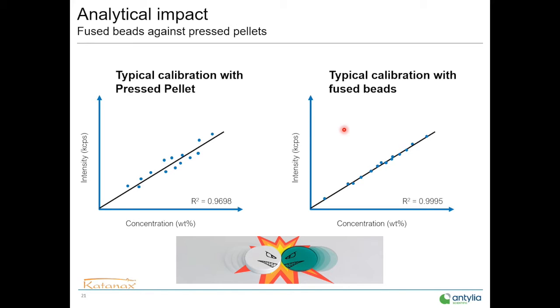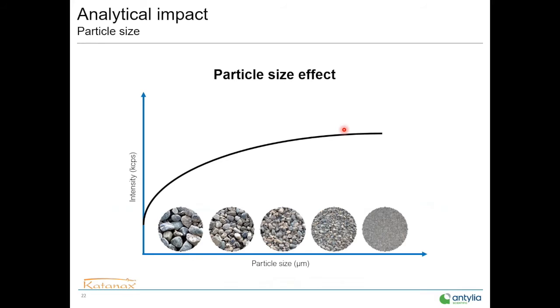The difference in analytical quality is mainly due to two factors. The first one is the particle size effect that can be observed in press pellet. Depending on the particle size of your sample, this will directly affect the intensity of a determined element. Particle size affects press pellet because the sample is ground and will end up with a certain particle size. This particle size can vary, and if it varies, it will vary the intensity of any element. In fuse bead, this aspect is completely eliminated because the sample is not particles anymore; it is digested and transformed into an atomic state where no more particle size effect will influence the quality of the result.